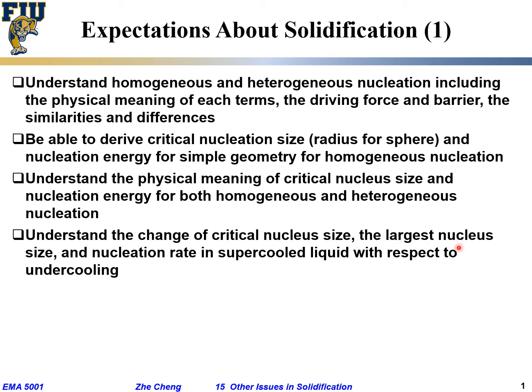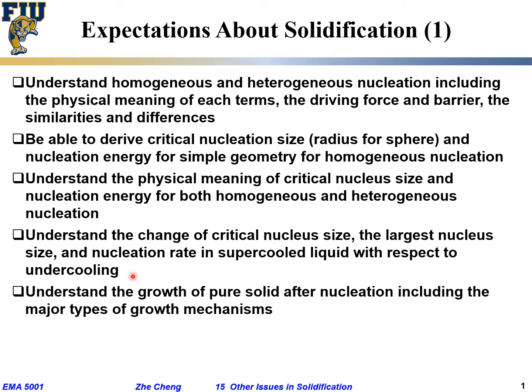The largest cluster size is the largest local region within the liquid that is arranged like a solid, like a crystal, and that increases mildly with increasing undercooling. When the undercooling is relatively small, the nucleation rate is essentially zero. But beyond a certain region, the nucleation happens dramatically. The nucleation rate goes up tremendously when the undercooling goes higher than a certain level.